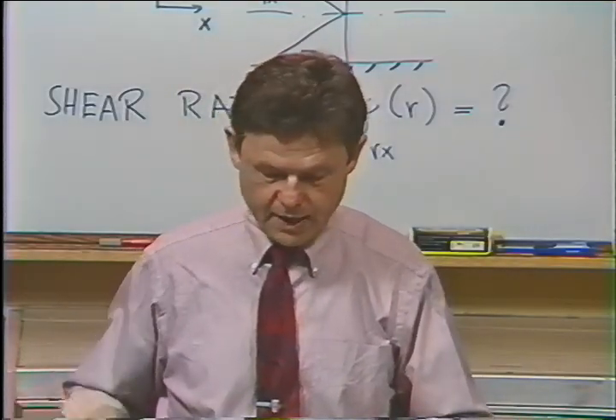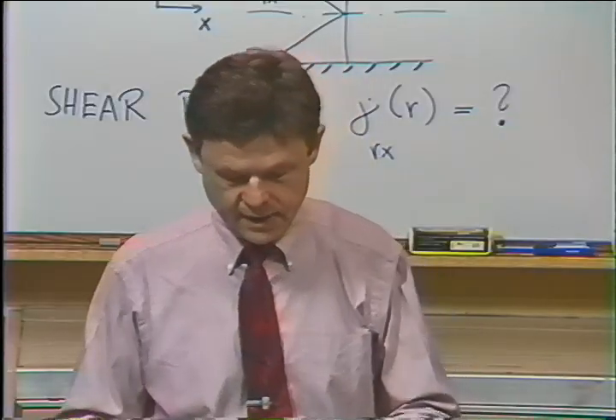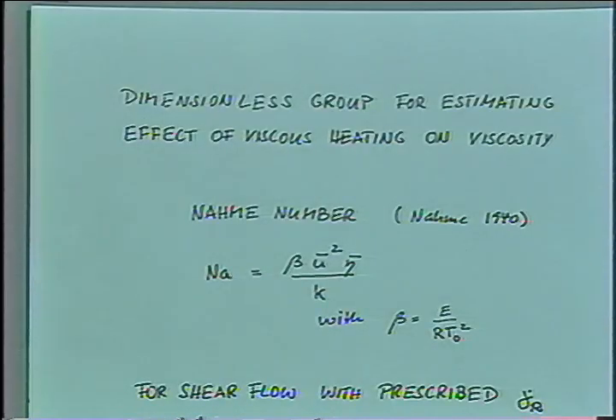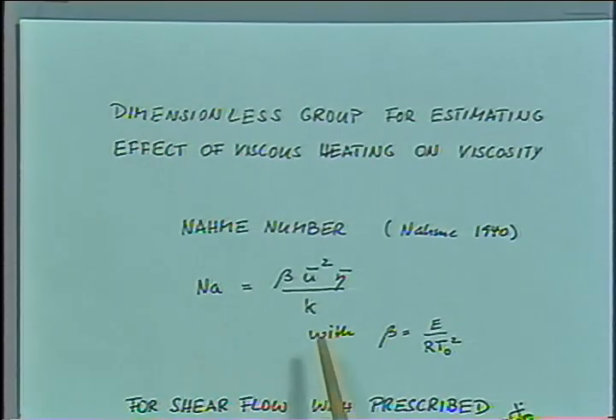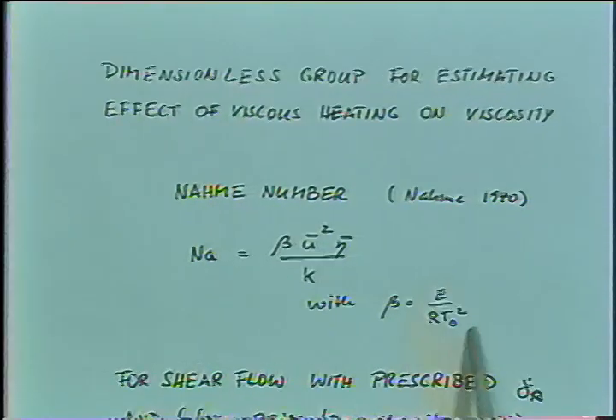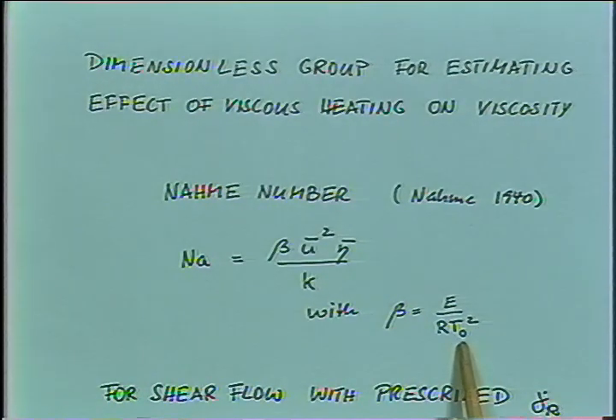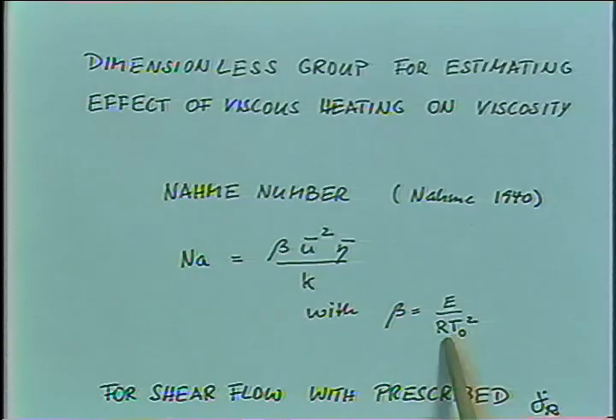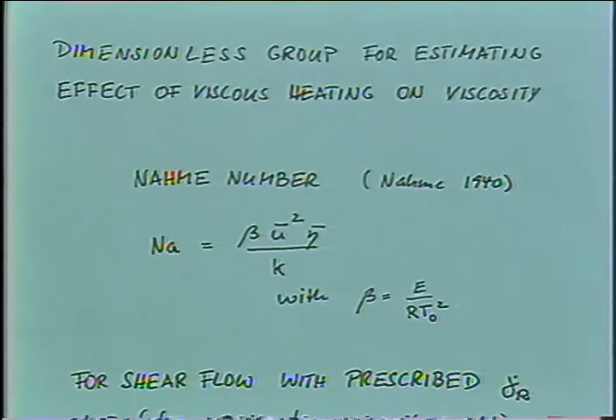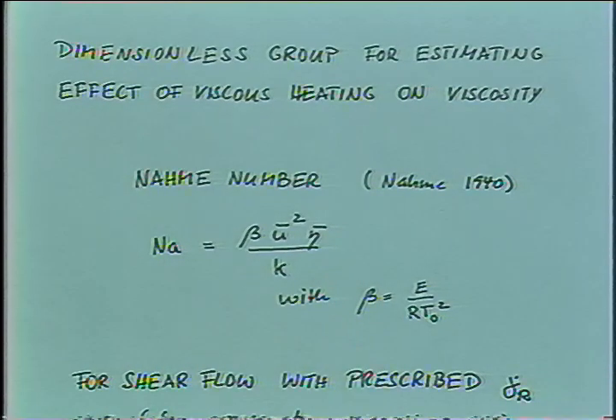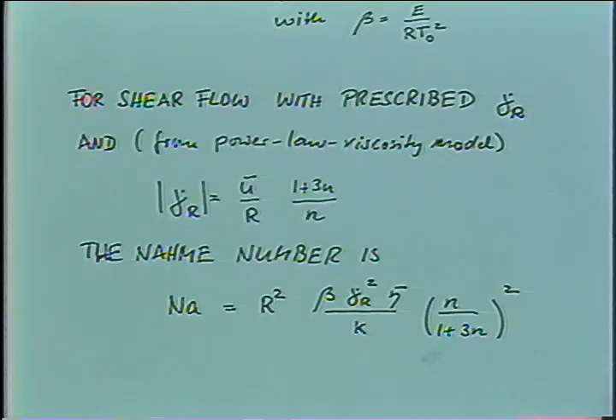We can see that also by just looking at the equation of energy, by looking at the viscous dissipation term and the conduction term in that equation. So when comparing the two and taking the ratio, if this ratio is very large, the ratio is called the Nahme number, this ratio is very large, then the viscous heating effects are very, very large. I included already beta here as the temperature coefficient of the viscosity. This would be derived from an Arrhenius temperature dependence. If you remember the temperature shift factor of the viscosity, this is a characteristic temperature difference derived from the Arrhenius equation. So if this Nahme number is large, then the capillary rheometry experiment is in problems.